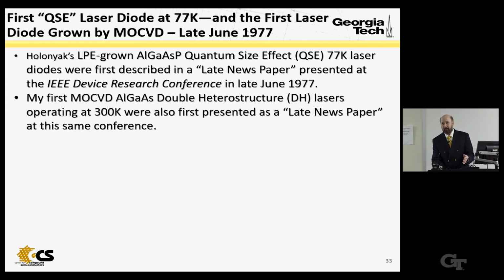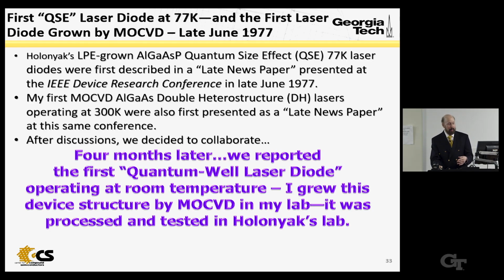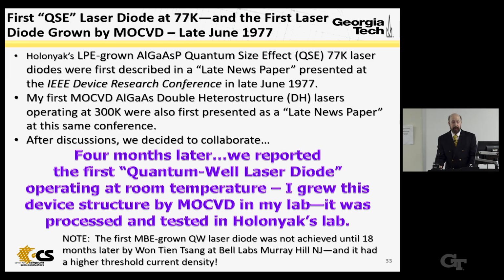And he said, "How did you do that, Dupuis?" And I sort of mumbled a few things. He said, "Well, let's collaborate." So 4 months later, we had the world's first quantum-well laser diode operating at room temperature. I grew it in my lab with that little MOCVD reactor you saw, and it was processed and tested by Holonyak and his students. The first MBE-grown quantum-well laser diode was not achieved until about 18 months later by Won-Tien Tsang at Bell Labs in Murray Hill, and it had a higher threshold current density. So, in fact, we were 18 months ahead of all the MOCVD groups as well. So it was 18 months before anyone had a quantum laser operating at room temperature besides our work.